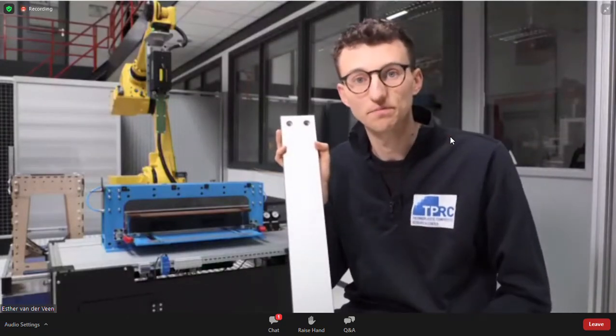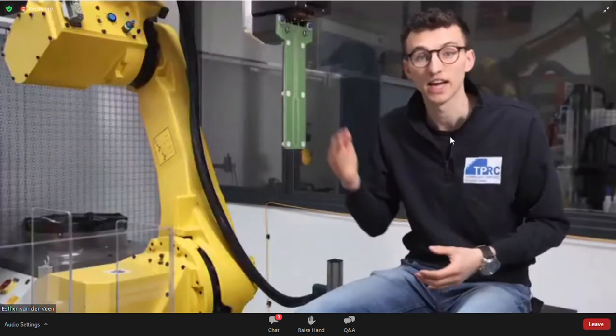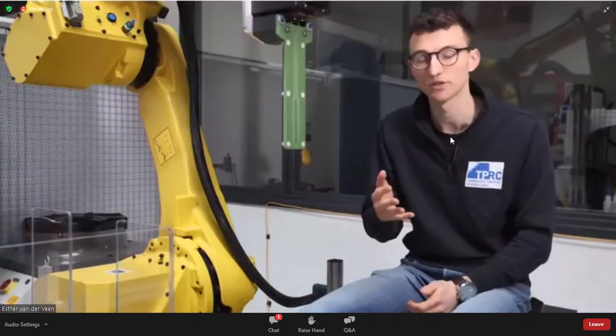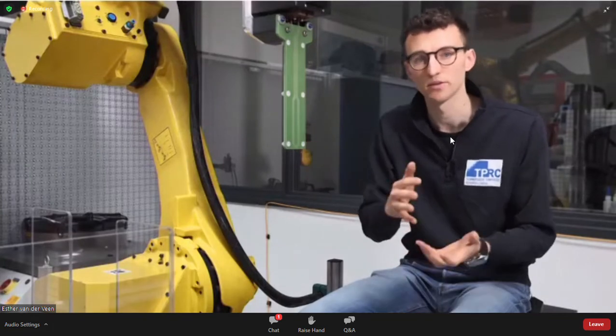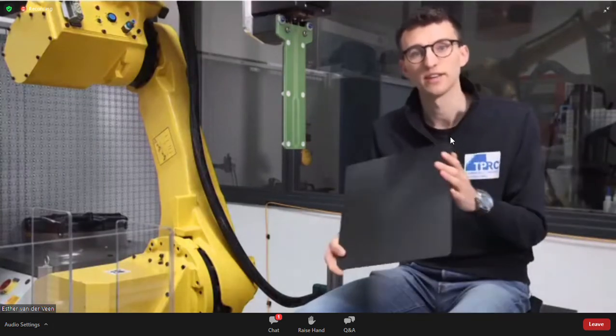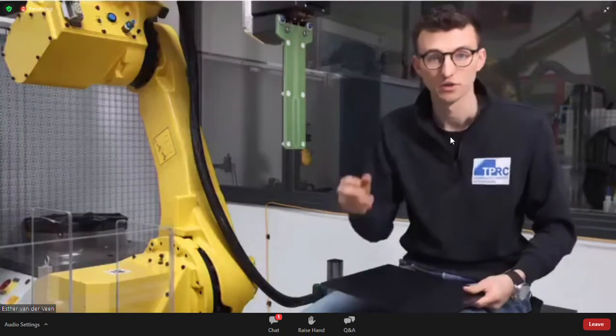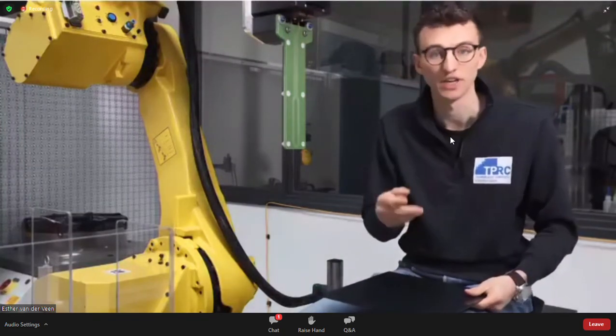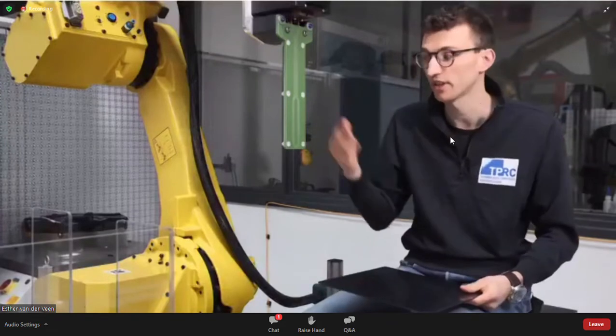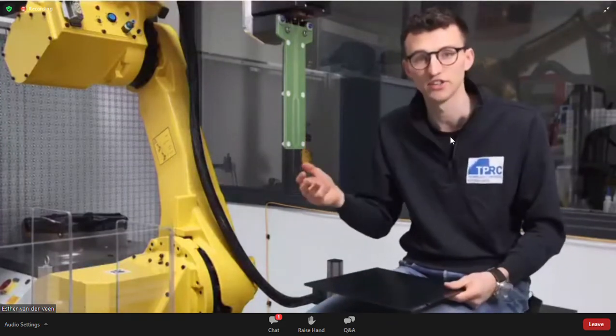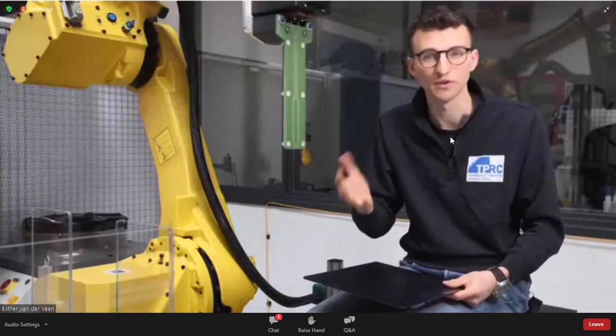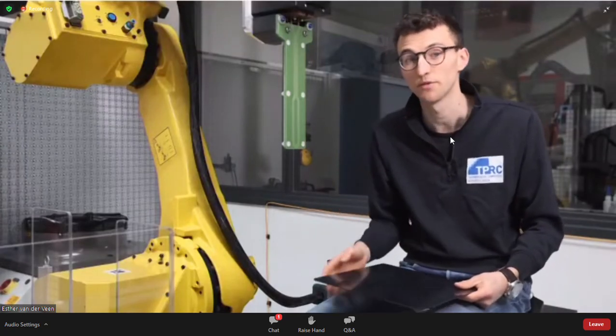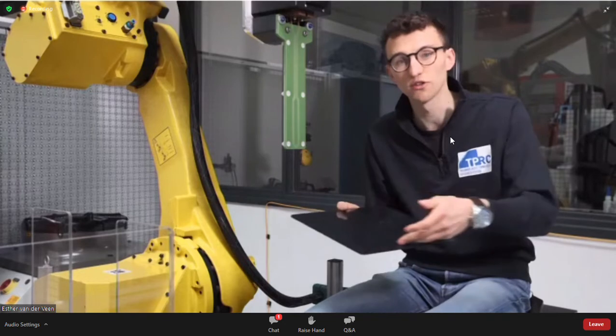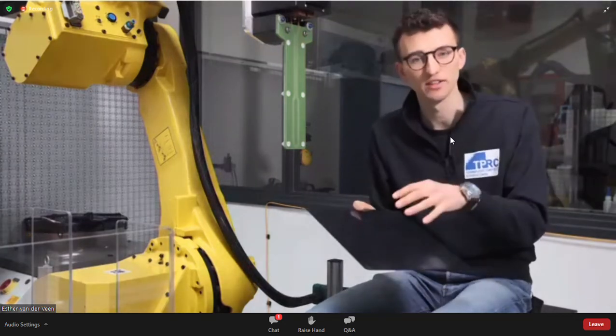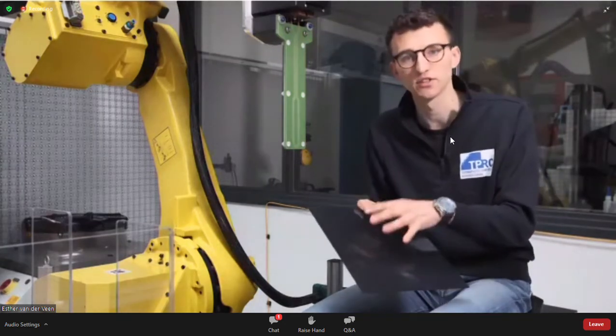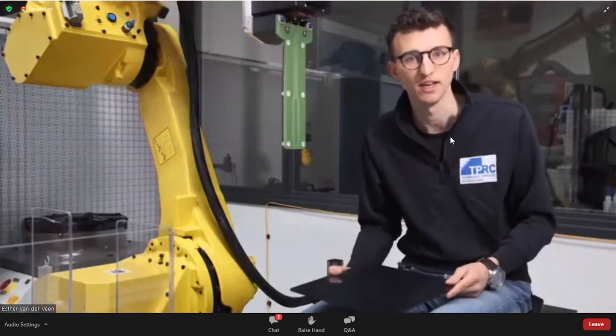changing magnetic field. A similar thing happens during the actual induction welding process, where in the experiment our coil is represented as a magnet and the aluminum was representing the carbon fiber plate. So in the experiment, the moving magnet would not result in large heat up in the aluminum, but imagine that now in the actual process, the field is changing at a very high frequency of 300,000 times a second. And at the same time, the field is way, way stronger. So the induced loops of electrical currents, the eddy currents, those will be met with the inherent resistance of the material, heating up the assembly locally.